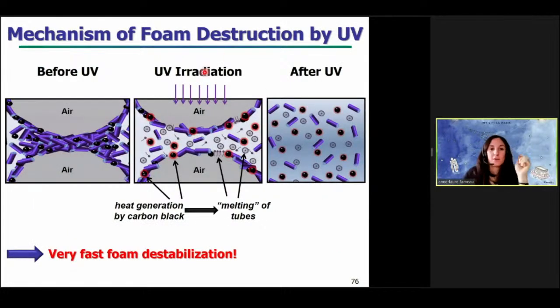So if I summarize the mechanism of foam destruction by UV: before UV, between the bubbles, you have this high quantity of tubes and carbon black particles. You apply UV radiation from the top of your foam. The carbon black particles absorb the UV light and transform this light energy into heat. And so the temperature inside the foam liquid channel increases above the temperature transition between tubes and micelles. So you don't have any more tubes to stabilize the foam. You have just spherical micelles. So you observe very fast foam destabilization.